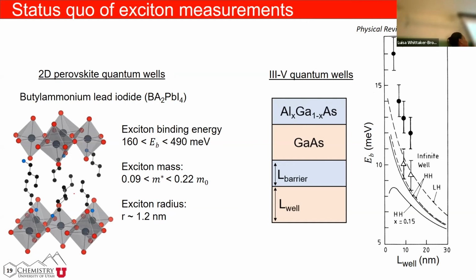So what is the problem? For example, I'm showing you this structure, butyl ammonium lead iodide, probably the most studied 2D metal halide structure to date. If you look at the values out there for the exciton binding energy, it varies quite a lot for this same material. It's the same system, and it goes from 160 to 490 milli-electron volts. This is the variation people have shown in the literature. There's only one paper talking about the exciton radius. Compared to gallium arsenide and aluminum gallium arsenide, the statistical variation in the experiment is much tighter, so there's not a lot of deviation there.